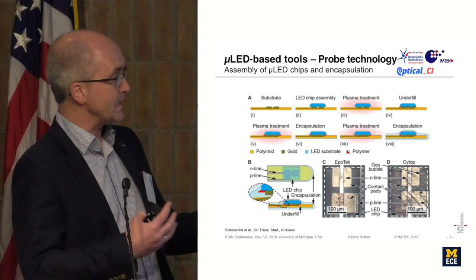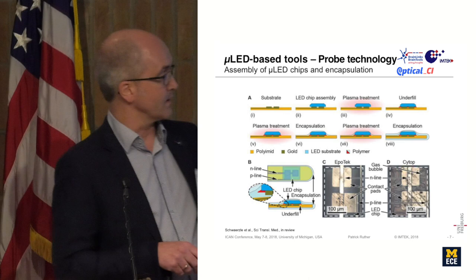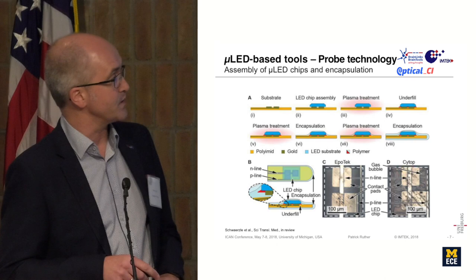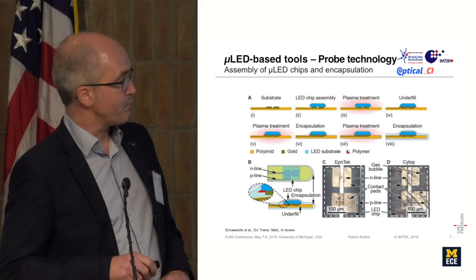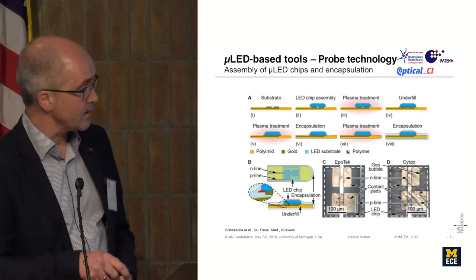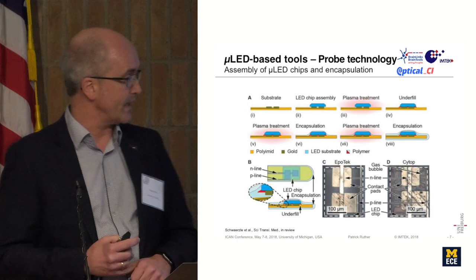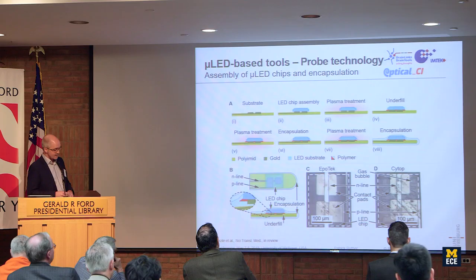And just one example that shows you the importance of which material is used at the end to fill the gap between the LED and the substrate. This is one example where we use an epoxide, and here in comparison, Cytop, a fluoropolymer that shrinks a lot, and we see all these voids around, that these are all open access ports for any liquid the probe is then exposed to.